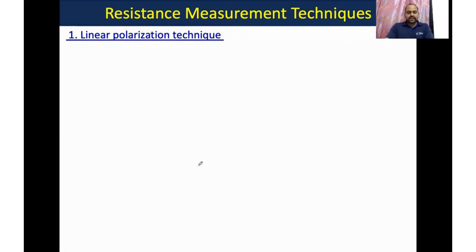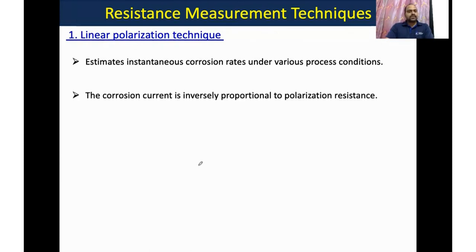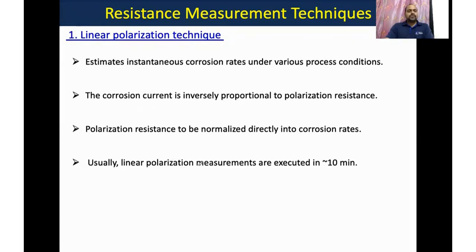The corrosion current is calculated using the Stern-Geary equation. Rp is already known. We have already discussed the Stern-Geary equation earlier. Use this formula, with the values of the anodic and cathodic Tafel slopes known, along with the estimated value of the polarization resistance. The Tafel constants Ba and Bc can be determined independently using the Tafel equation, or by using the Tafel technique, we can calculate the values of Ba and Bc independently in another experiment with the same setup, and then measure the I corrosion.